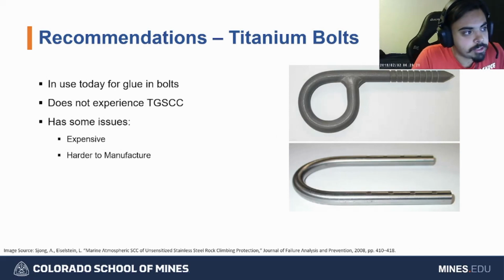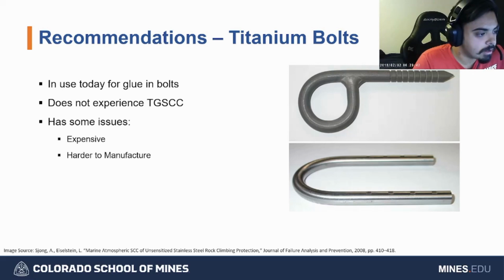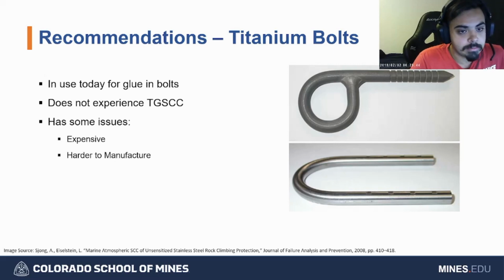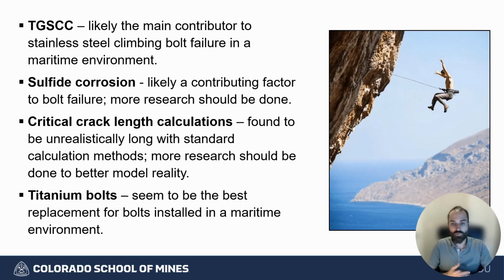You could just bypass the issue entirely with titanium bolts. These titanium bolts are in use today with glue-in bolts, and they don't experience transgranular stress corrosion cracking at all. So it's a much better solution because it just bypasses the problem entirely. But they're expensive because titanium stock is more expensive than steel by default. And it's hard to manufacture as well because these bolts can't be cold rolled like steel. Titanium doesn't do cold rolling well, and you can't manufacture them on such a large scale as you manufacture steel parts because of that.